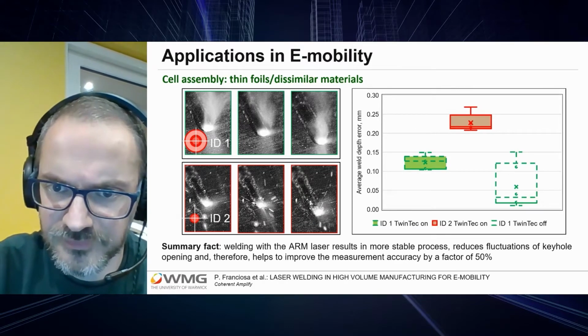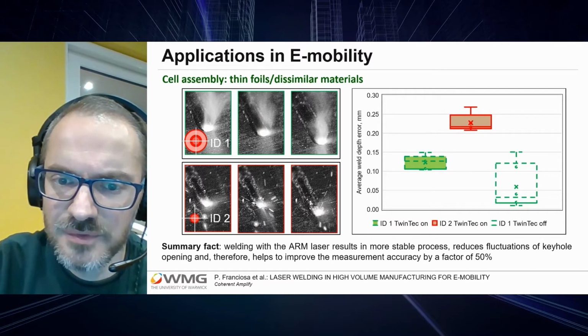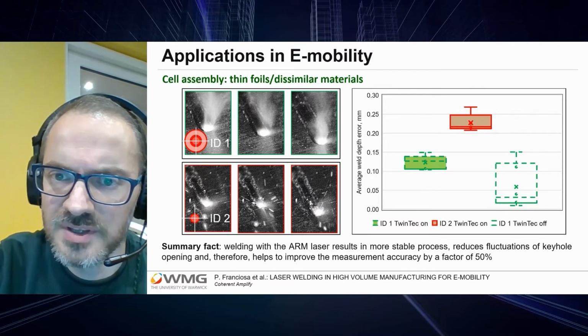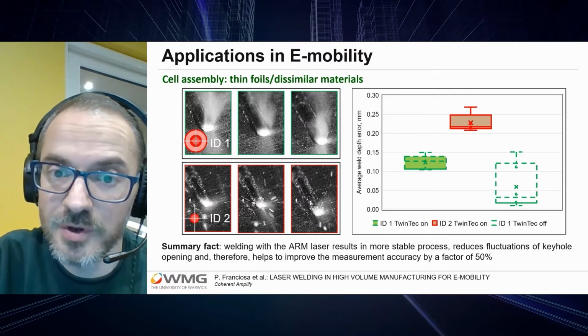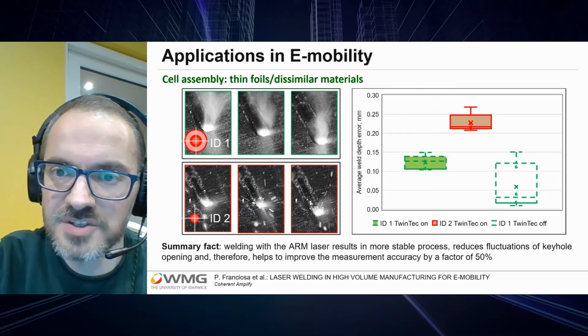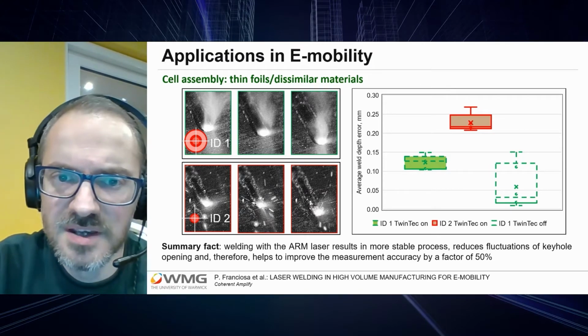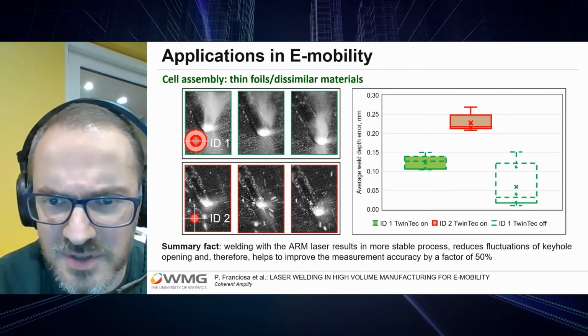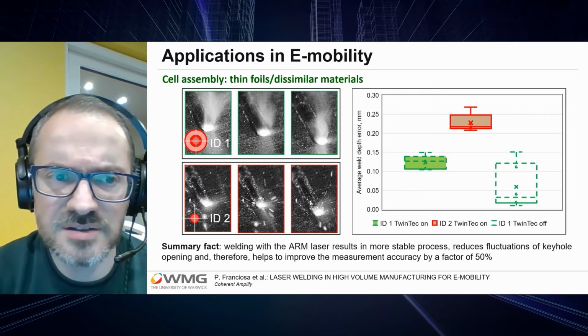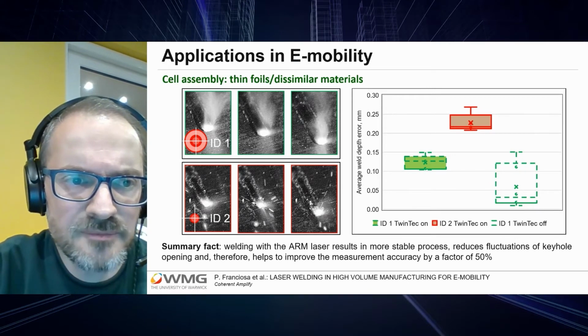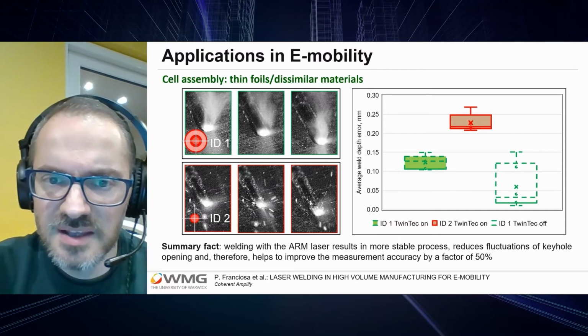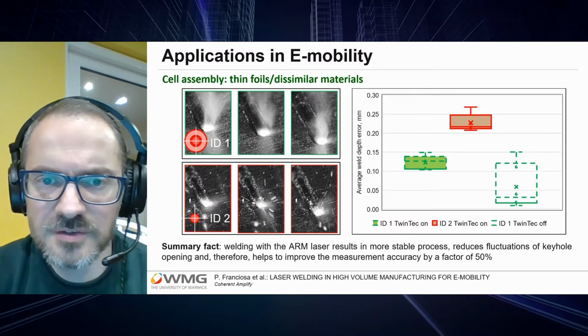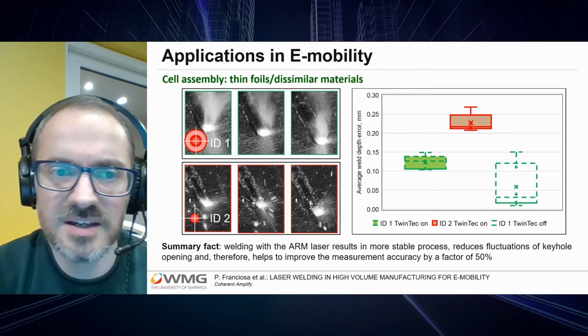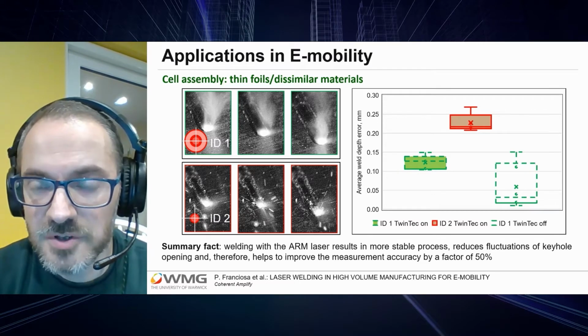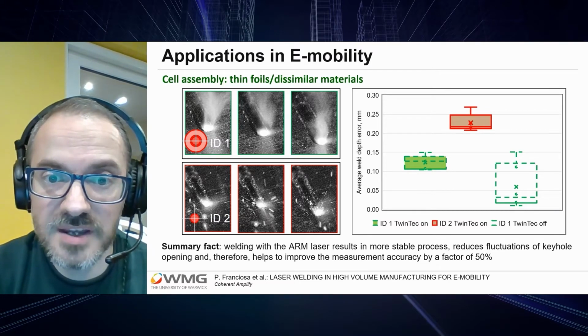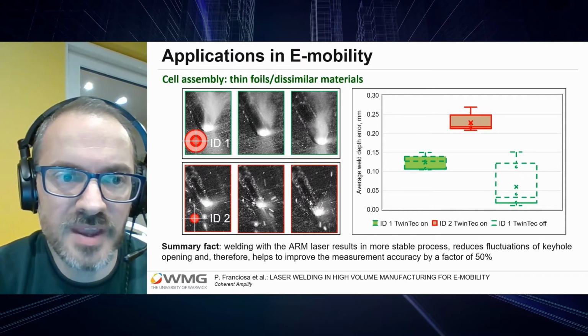This is what we have done and what I'm showing within the slide. So if you consider ID1 TwinTec on and ID2 TwinTec on, the first two box plots on the right-hand side chart tell us that the average weld depth error is significantly reduced in the case of ID1. ID1 again is the case with the core plus ring together. And the error we are plotting is the error between the OCT measurement and the measurement we take directly with the destructive cross-section. So there is almost 50% reduction in error by using this core plus ring.